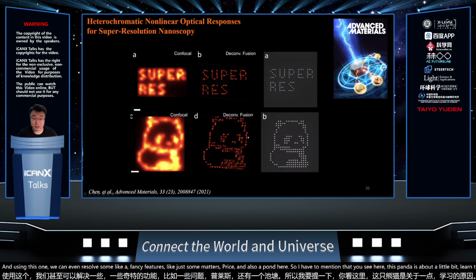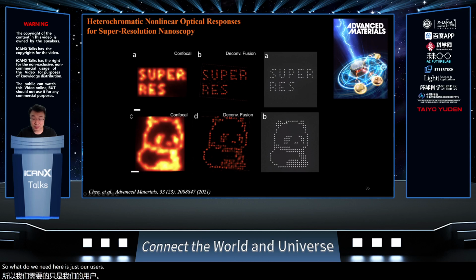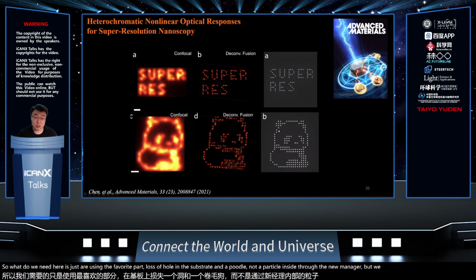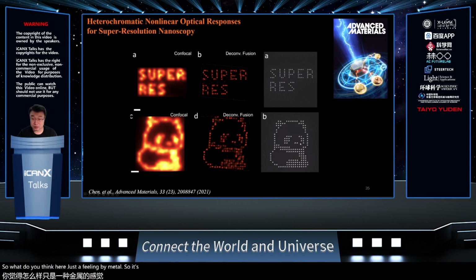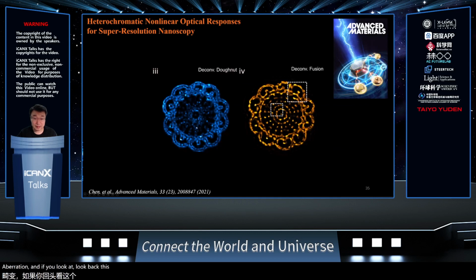I have to mention that you see this panda is a little bit blurred. The reason is we couldn't control well putting the nanoparticle in each hole. What we did here is use the FIB to punch lots of holes in the substrate and put nanoparticles inside to do the imaging, but we couldn't control making one hole get one particle. So what you're seeing here is just filling by metal. It shows a really regular pattern here, but filling with nanoparticles is quite hard. Even so, compared with the confocal, you can see that we have really good resolution and good control on the aberration. And if you look back at this mooncake structure again, you find it's actually lots of dots, rather than this blurring feature.